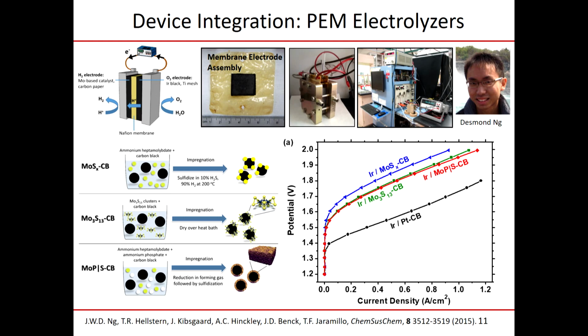But if you swap out that platinum for these different sulfides and phosphosulfides, you see that you pay only a small penalty of 0.2 volts. Now, in a perfect world, we pay 0 millivolts of a penalty, and we can get a polarization curve that looks just like the platinum using a non-precious metal. But like I said, no human has ever developed that just yet. And so there's still a challenge to be had.